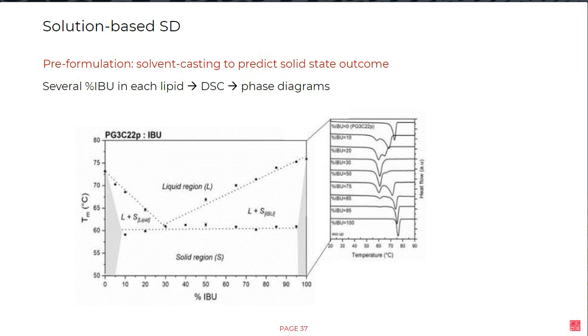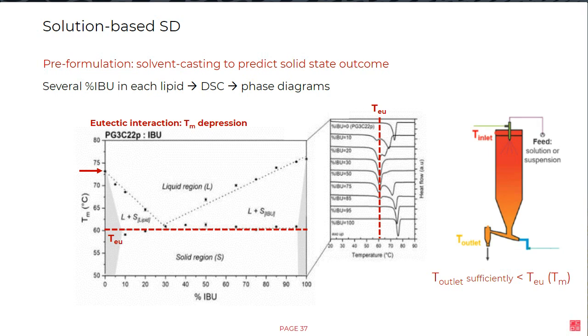So the very clear observation here, the first one, is that even though we have lipids with high melting point, like around 74 degrees, any kind of interaction with ibuprofen will immediately drop the melting point of the mixture. And what we are seeing here is a eutectic interaction among these two components, which is characterized by melting point depression. And what we see here is that now the real melting point of the formulation is not actually the matrix, 74 degrees, but the eutectic temperature, which is quite lower than 60 degrees. So very first observation is, okay, we need to provide an outlet temperature sufficiently below the new melting temperature of the formulation. And how is sufficiently below? We will see in the next slide what is the recommendation on that part.